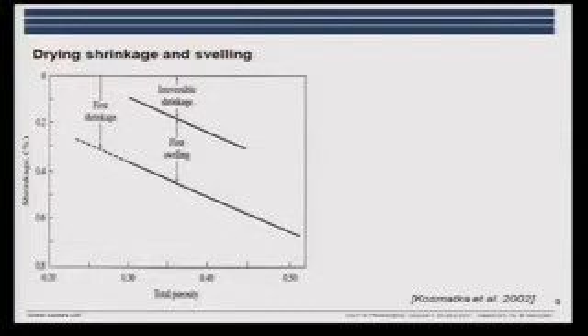So, the conditioning. If you take a sample, a concrete for instance, and you look at the drying shrinkage. Initially you mix it and it cures, and at a certain time you will expose it to some environment, and often it's not a totally wet environment. So you have some drying, and here we have the shrinkage in percentage as a function of the total porosity. And what you see here, initially, we have a shrinkage called here the first shrinkage. Then if we wet the sample, we will have swelling and expansion of the material. But we also see that there is some of the volume change which is not recovered, some irreversible shrinkage. There seems to be a change in the structure of the material.